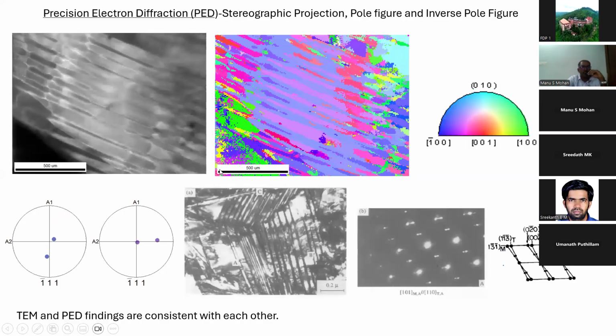So now it comes to my data. I'm sorry that the scale bar shows micron, actually it is in nanometers - some mismatch was there, that is why it shows micron. So this is the TEM data. Now you see the TEM image, this is in nanometers, please bear with me, it is shown as microns. You can see 5 nanometer twins here. So that you see in the inverse pole figure.